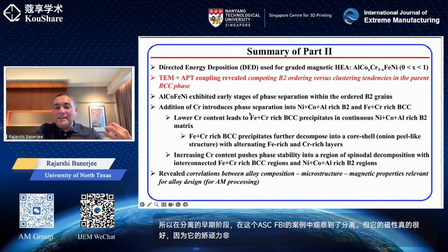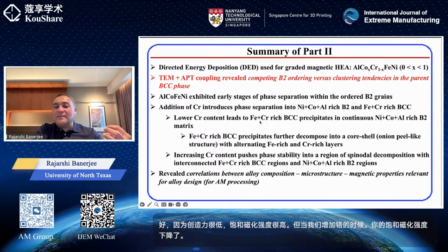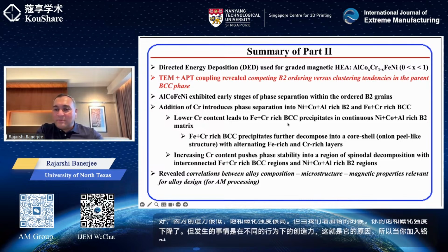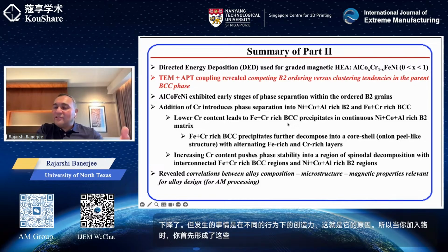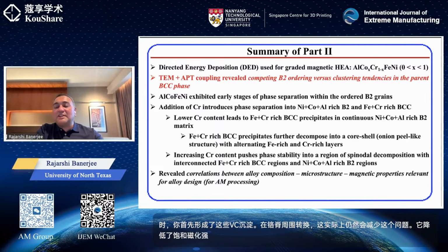But as we add increasing chromium, the saturation magnetization came down, and the coercivity had a different behavior, and these are the reasons for it. When you add chromium, you first form these BCC precipitates, which are iron-chromium-rich, and that will reduce the saturation magnetization but increase the coercivity, because you are introducing these precipitates which can be barriers to magnetic domain wall motion.